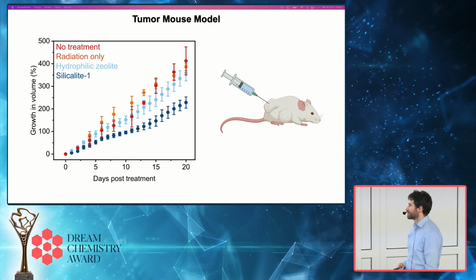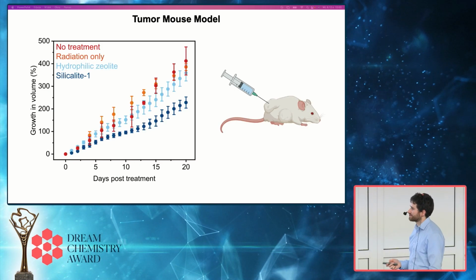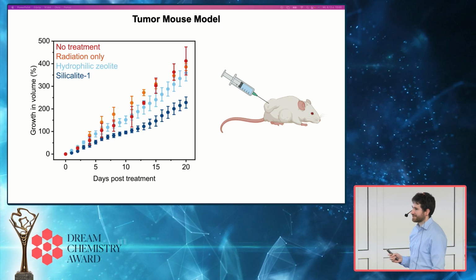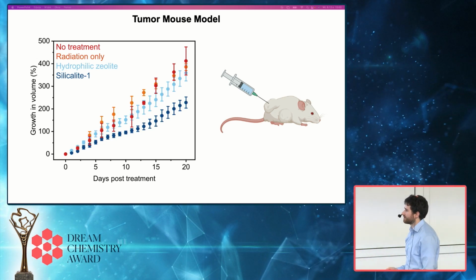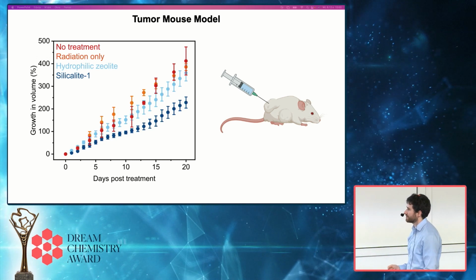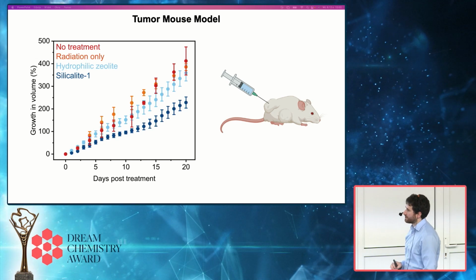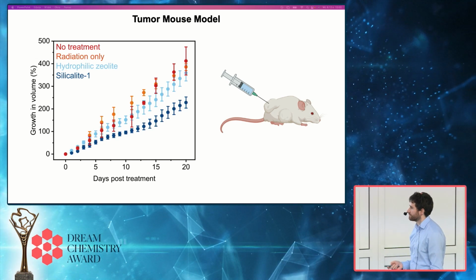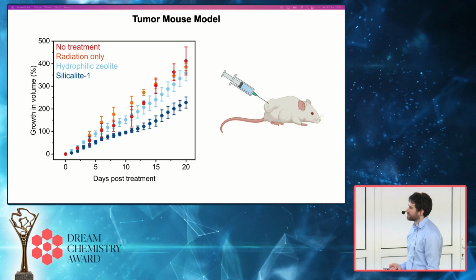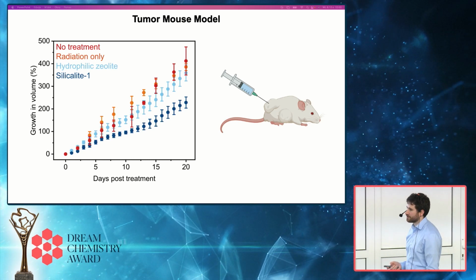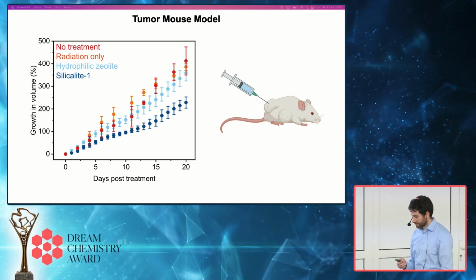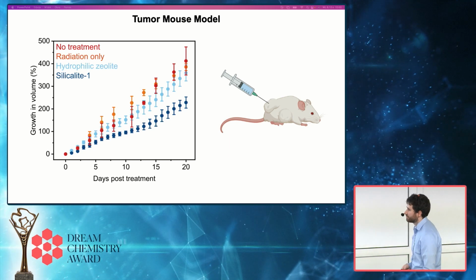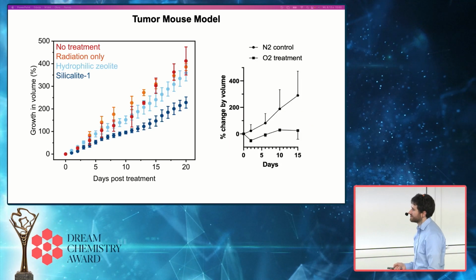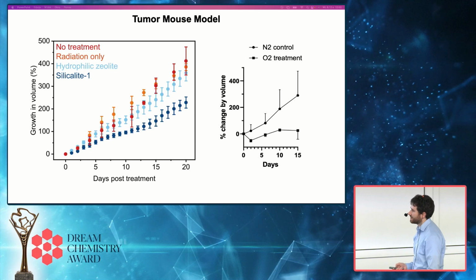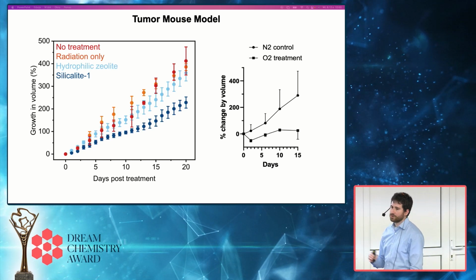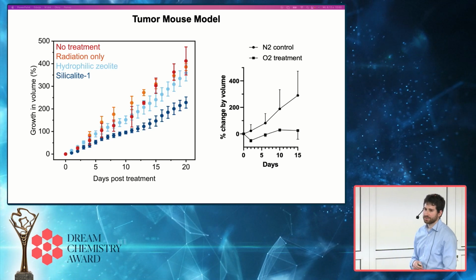And so we did an initial proof of principle experiment where we demonstrated, without really any optimization, that we could inject our hydrophobic zeolite nanoparticles in water prior to administering radiation for a mouse tumor model, and show that we could significantly slow the growth of a tumor compared to control experiments by providing the source of oxygen. If we inject the zeolite with just nitrogen rather than oxygen, we see no change in how quickly the tumor is growing.